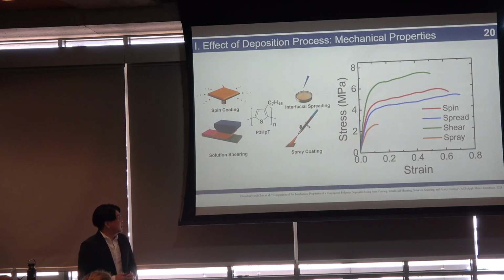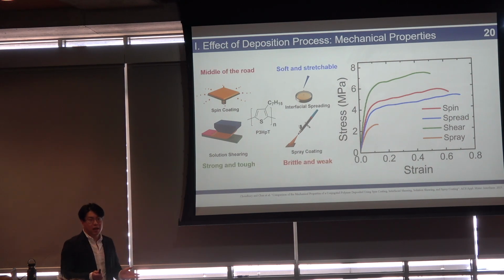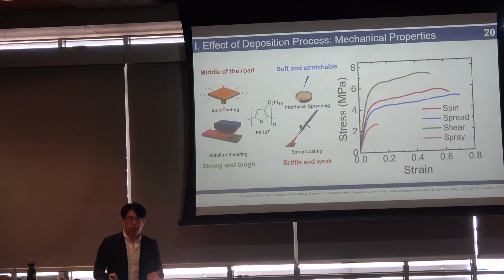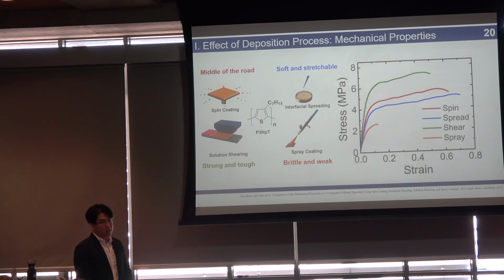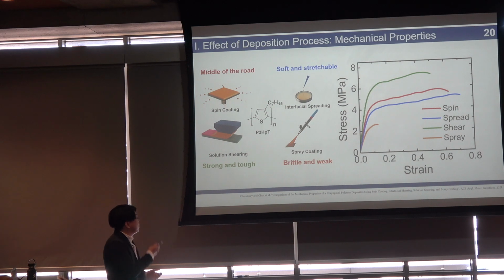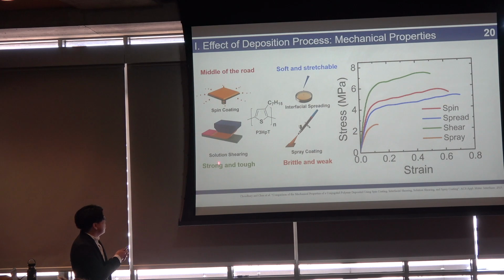So here are our results. We did mechanical testing on each of these, and these are representative curves that are shown. And basically, we can summarize this with the following. Spin-coated films are generally middle of the road. They're no better or worse than anything else. Interfacially spread films tend to be more stretchable than other films. Solution shear films tend to be extremely strong, and spray-coated films are very brittle and weak.